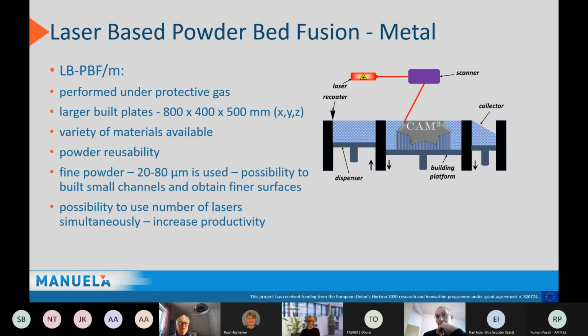Roughly fine powder, 20 to 80 micron, is used. We can build quite small channels, and we can actually create decently fine surfaces here. There are instruments out there where you can use a number of lasers in parallel, which increases productivity, but you can also work to increase the productivity by tuning the printing parameters, for example, increasing layer thickness. So that is how the technology is today.